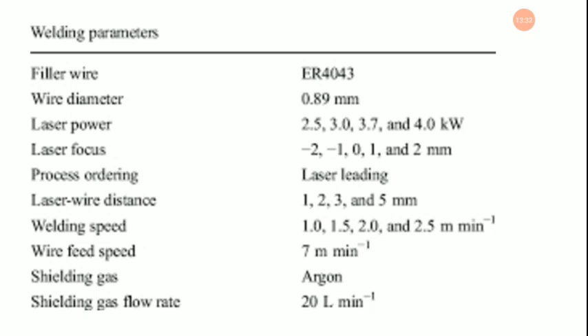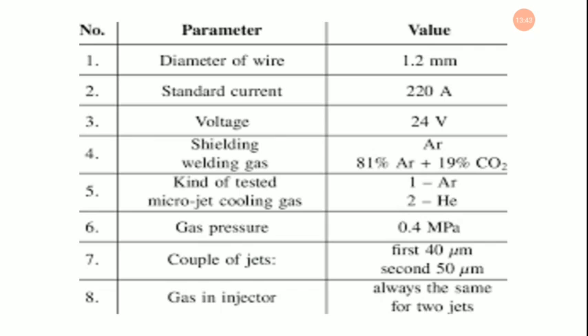In our testing procedure, the first test was the hardness test. For the hardness test, we made different test specimens. We cut a piece of 10 millimeters from the length of the welded pieces, and we made 50 pieces of weldment for the hardness test. Before the hardness test, we need to make the surface of the piece smooth after cutting. For making it smooth, we are using emery papers of 220, 320, 400, 600 grade, until we got the smoothness required. After getting appropriate smoothness, we did a hardness test for the parent material and the welded zone. In the hardness test, we found the hardness of the material increased after welding.